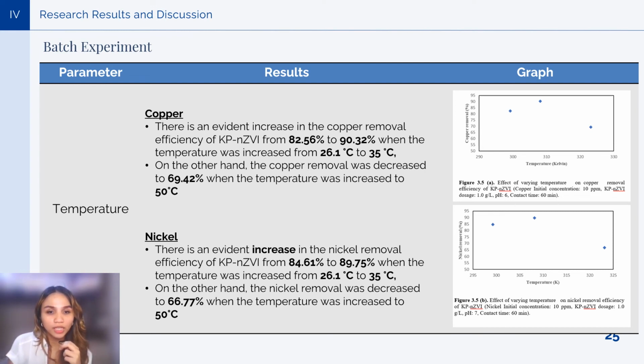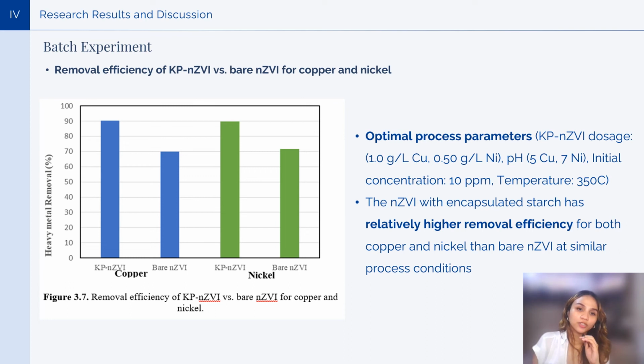The same goes for nickel, there is an increase to 89.75% when the temperature is increased to 35 degrees Celsius. At 50 degrees Celsius, the nickel removal was decreased to 66.77%. The last part of the result is the removal efficiency of KP-nZVI versus the bare nZVI for both copper